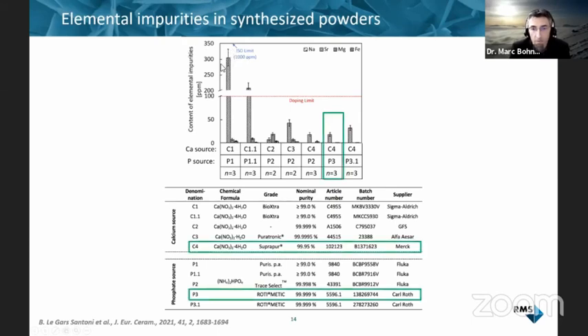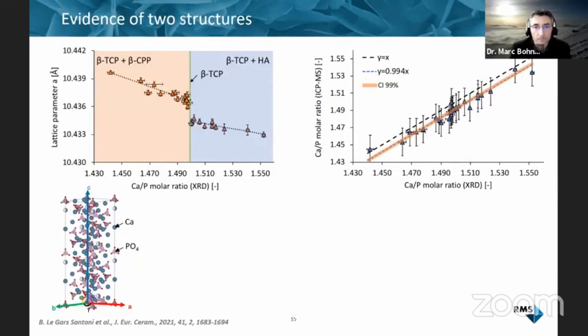So it took some time for Bastien to find raw materials that were pure enough to produce a beta-TCP that has a very low amount of contaminant, in that case 20 ppm of strontium. And we had no other contaminant like that are listed here. Actually we did a screening by ICP-MS, and we had over 40 different elements, or 47 I believe. Strontium was the highest amount. So we can say that we have what we could call a pure beta-TCP.